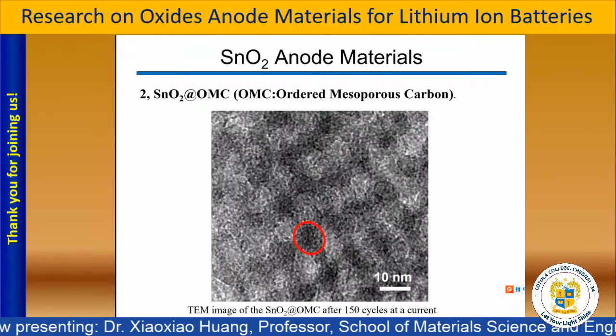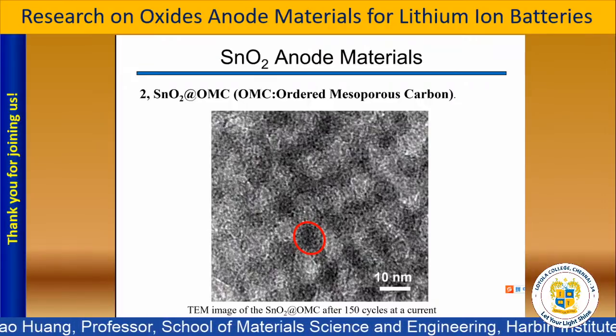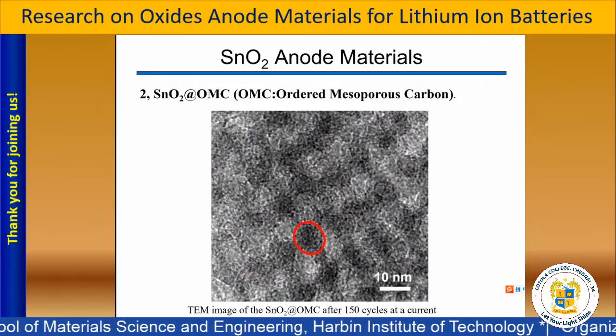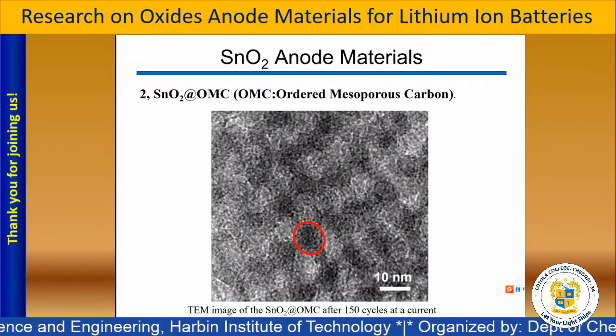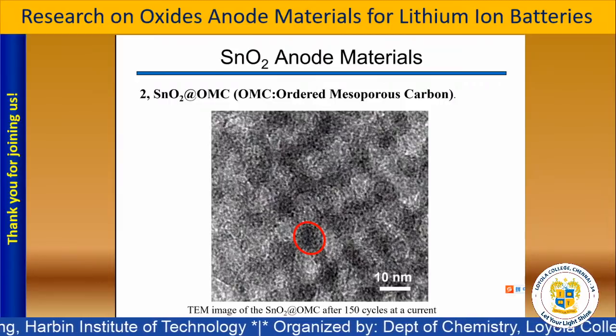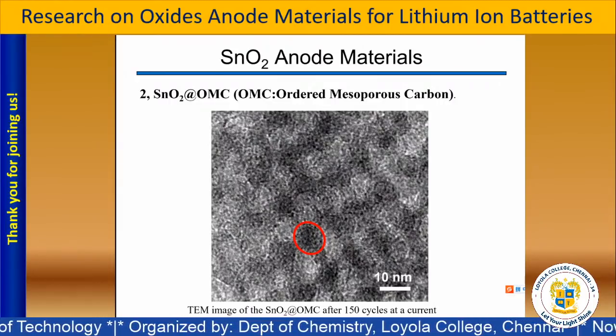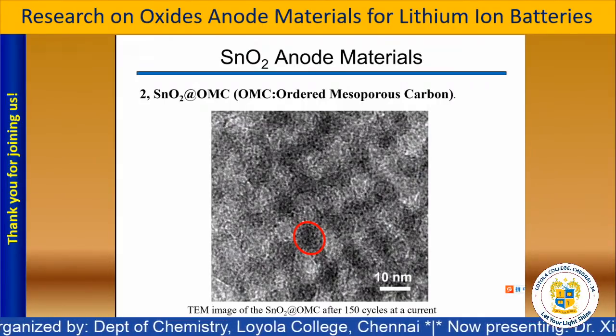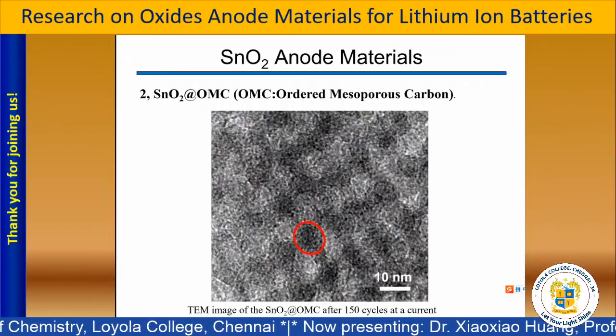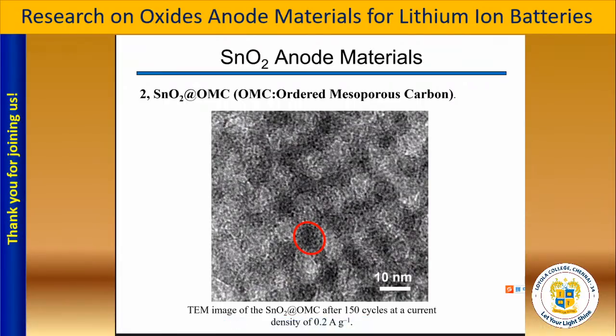This picture is very interesting because we tested the tin oxide OMC material after 150 cycles. That means we tested the material and then took it to test again, and we can see that the structure has been maintained. It is not broken or greatly changed, even after a long time of cycling.